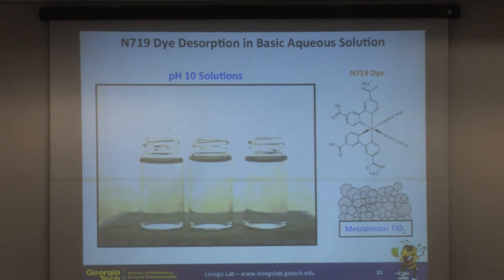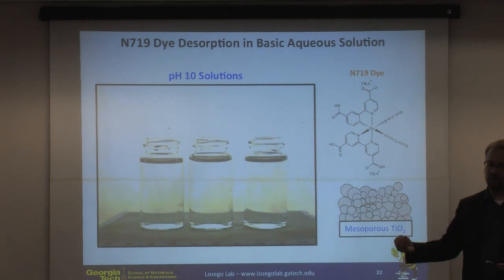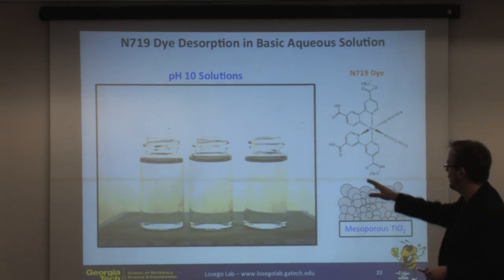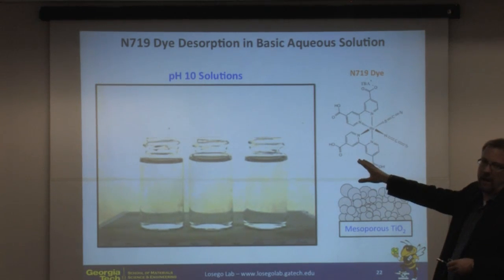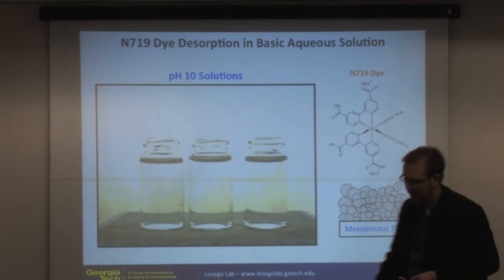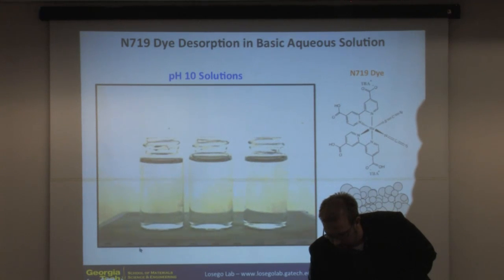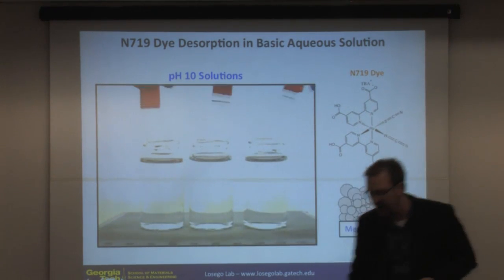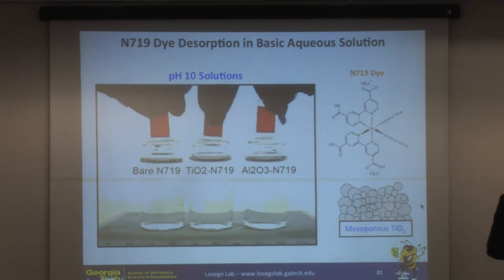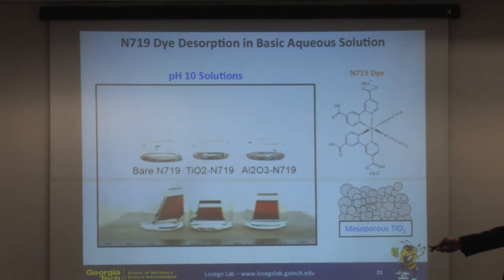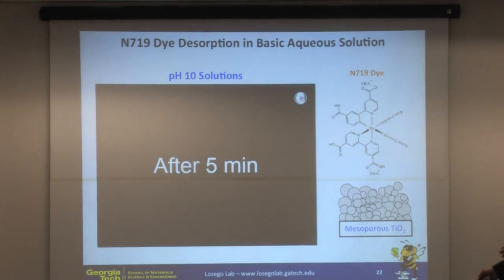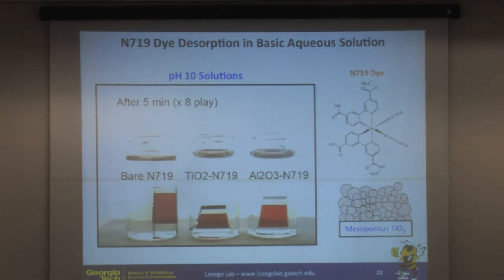I'll show you just a quick movie of if we take these slides, so the dyed slides, and we place them in a high pH solution. So we know high pH should strip the surface of all the molecules. And so you'll see we have one that has just been dyed, and then two that have been ALD treated after dyeing. And we'll see the dye molecules in real time actually being stripped off of the electrodes. So the bare here, treated, okay performance. The alumina is even better performance.